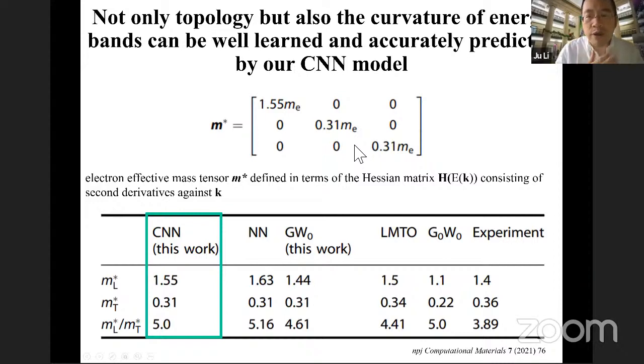And now, for those who have worked with neural networks, we have, for example, done quite a bit of fitting interatomic potential with neural networks. There is an issue of taking derivatives of this network that sometimes is a bit noisy. And so in this particular case, we are looking at the second derivative of the electronic band dispersion, which is the effective mass matrix. And we're able to show that this improved neural network can give this second derivative, which is the effective mass, related to the mobility of the carriers, pretty accurately compared with experiment.